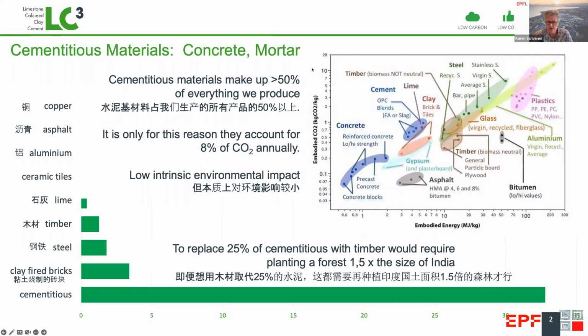The context of this is that materials based on cement make up more than all other materials put together. It's purely for this reason that they account for such a high proportion of world CO2 emissions. As you can see on this graph at top right, the embodied CO2 in terms of kilo per kilo is some of the lowest of all materials. So we're not going to improve from a CO2 perspective by replacing cement with other materials, and we simply don't have enough resources for other materials.